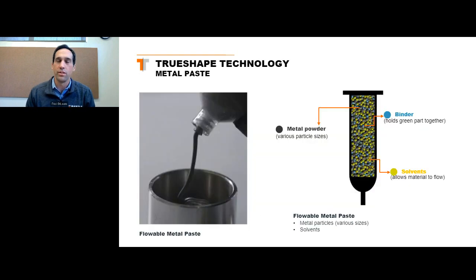So the tool steels, how do the tool steels work? Well, what's unique about Mantle's process, and one of the unique aspects of our technology, is that our tool steels start their lives as pastes, metal pastes. You can think of it like a toothpaste or a thick paint in terms of its consistency. And essentially what it is is a combination of metal powders, metal particles, a little bit of binder or glue to hold everything together, and some solvents that allow the material to flow together. And this slurry is what we print. So we print this paste, we deposit the paste, and we extrude it in a manner that's similar to many other types of 3D printing, where you extrude a material and build something up layer by layer.